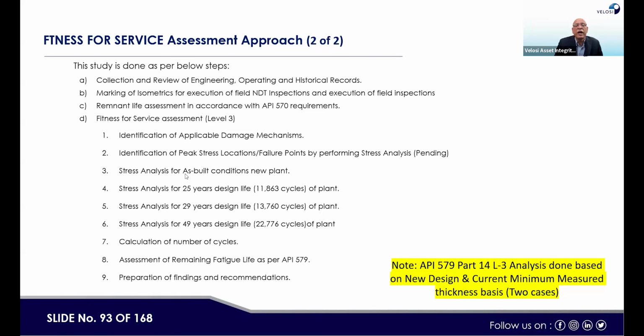So stress analysis for the as-built condition, or as a new plant, then stress analysis for 25-year design life with 11,863 cycles, stress analysis for 29 years design life, 13,760 cycles, then stress analysis for 49 years design life with 22,776 cycles. Calculation of the number of cycles is also done based on the operation mechanism or scenario of the particular plant. Then assessment of remnant fatigue life as per API 579, preparation of findings and recommendations. So these are basically the steps.